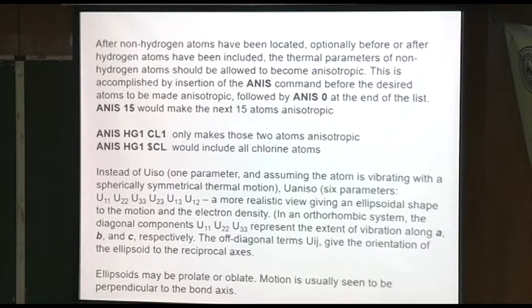Usually you write in the SFAC list, you would put carbon first, hydrogen second, and then other atoms. U ISOs, if everything is right, usually doesn't go much further than .02 to .08 angstrom squared. I look a lot at the U values because they tell you a lot. If the atom you have selected is too large, then these will get too small. Let's say you have a carbon and it's actually an oxygen, but you've put it in as a carbon. Then the thermal parameter will be too small.